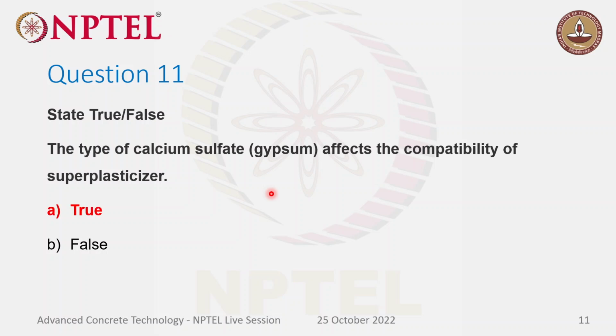The answer is true because calcium sulfate will have sulfate in it, and superplasticizer will have sulfonates in it. Both of these sulfates and sulfonates will concentrate on the alumina sites from calcium aluminate. So during that time, there will be conflict between the calcium sulfate from the gypsum and the sulfonates from the superplasticizers. So we have to consider the type of calcium sulfate we are using, and how we can reduce the compatibility issues between the superplasticizer and the gypsum type. Okay.